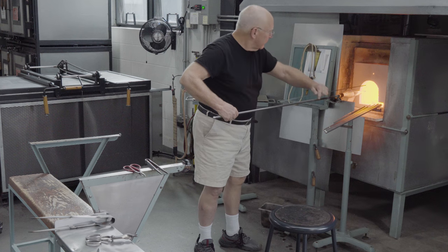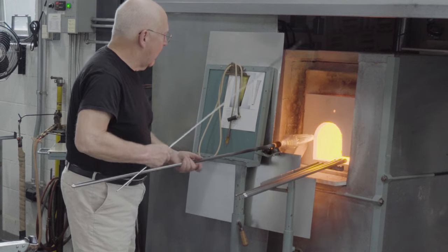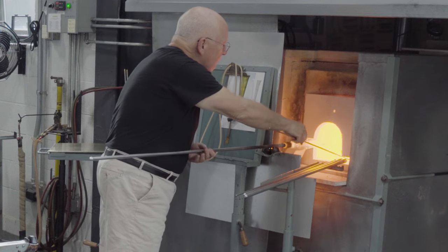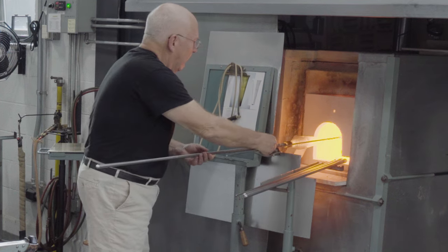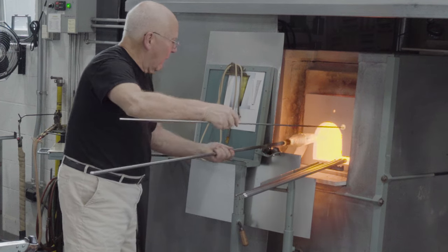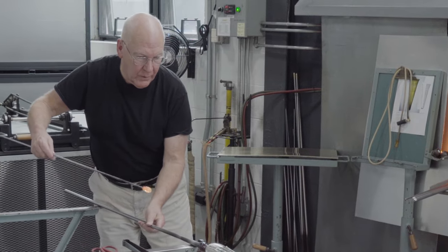A critical part of the process is keeping the spiral thread hot enough so as not to crack. So after I've gathered the next loop, before I begin the loop, I flash the uppermost part of the vessel to ensure it's staying hot enough to protect the thread.